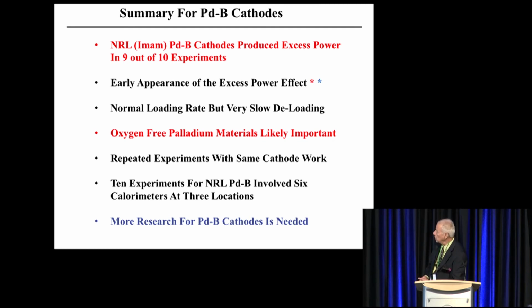So anyway, this is a summary. The Palladium-Boron cathodes made by Dr. Imam at NRL that I've run gave excess heat in 9 out of 10 experiments, and you might even say 10 out of 10, because the one that didn't work had a reason for it, and it may also have shown a little bit of excess power. And excess power comes very early, in fact almost instantaneously, if you really look at it carefully. The main reason for that, I think, is the reaction of deuterium with boron. But eventually it goes back to normal, and that reaction will stop. As far as I can tell, it's the normal loading rate. I mean, the loading curves look very similar to palladium. But